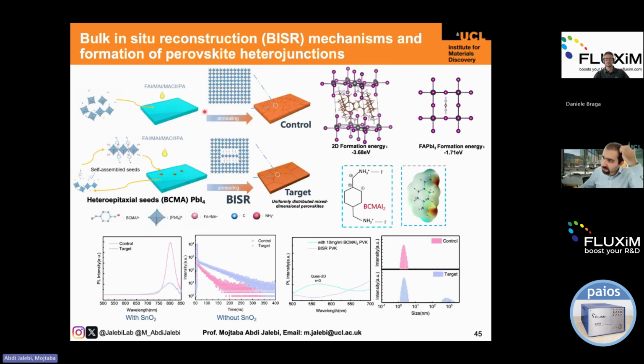So, the approach that we use here is we utilize self-assembled seeds of 2D material in the perovskite 3D precursor, and that helps us to form 3D perovskite around the 2D perovskite, as supported by our calculation as well. And we observe the 2D phase in the experimental methods we use, in DLS and also in the PL as well. And overall, it helps us to enhance the grain size, as well as higher PCE, and more importantly, more stability. As you can see, these are the thin film stability, and these are the device stability, significantly better, even at large size as well.